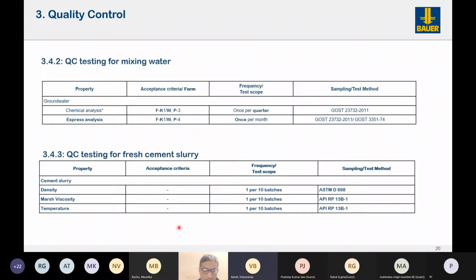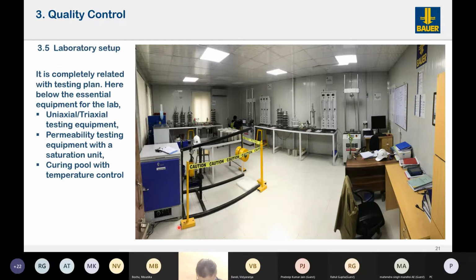And also mixing water, we have to check for the chemical analysis and express analysis. Then the cement slurry, we have to ensure the slurry is having the proper density, Marsh viscosity, and the right temperatures so that the composition of the mixed slurry is not distorted.